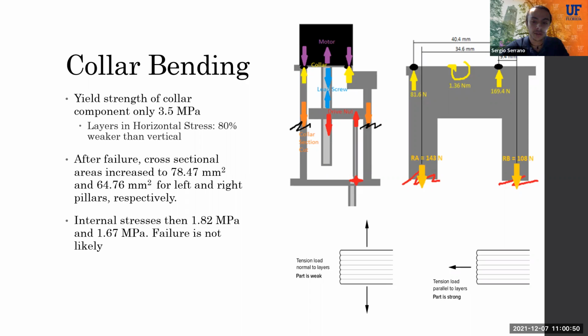Furthermore, it was noted that during the preliminary test when failure occurred, the motor was improperly fastened to the collar with only half of the necessary support screws. This would cause an increased moment and internal stresses in one of the pillars and likely cause failure. After this failure, proper assembly was ensured. The cross-sectional area of the pillars were made thicker, and analyses showed that failure due to these tensile stresses would not be likely.